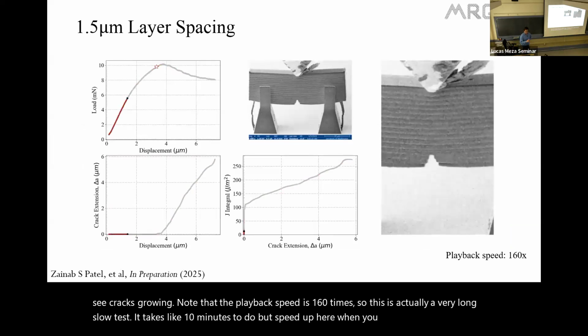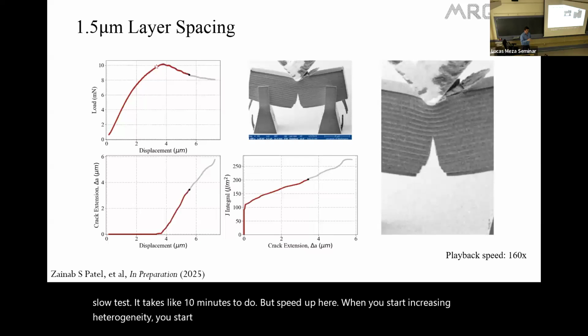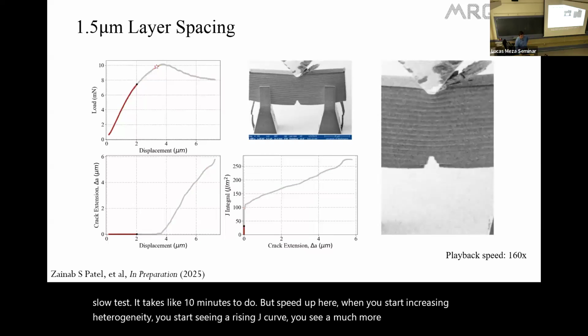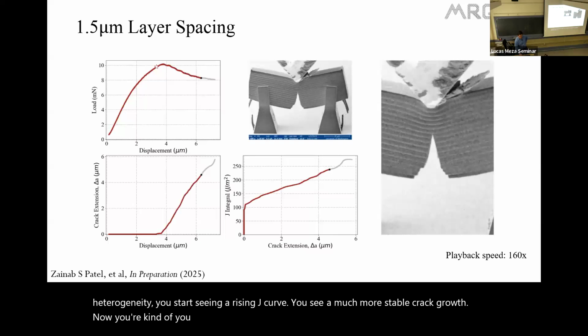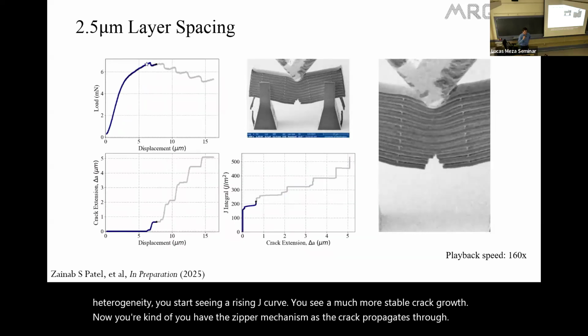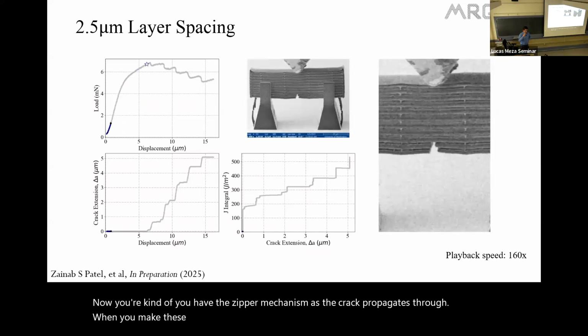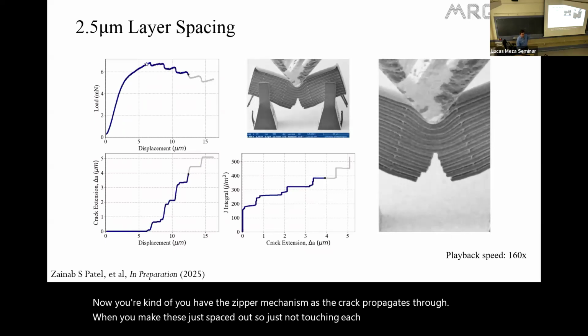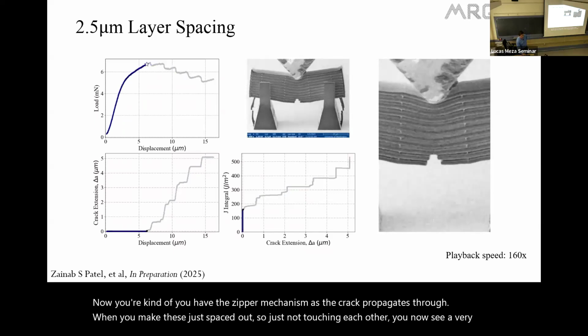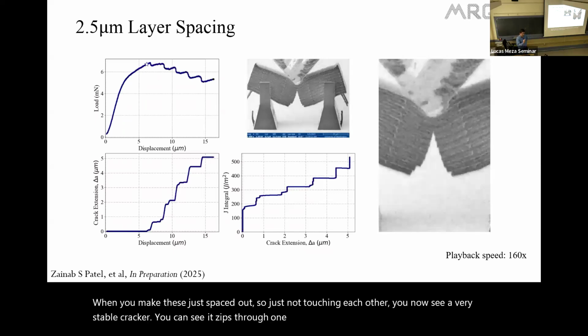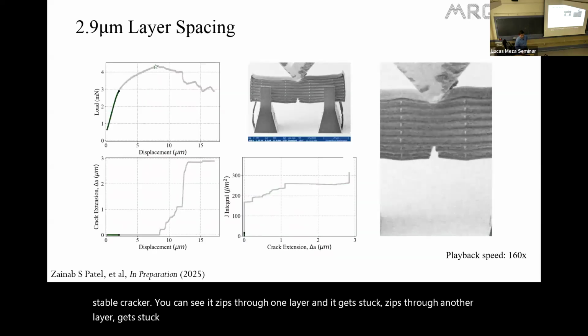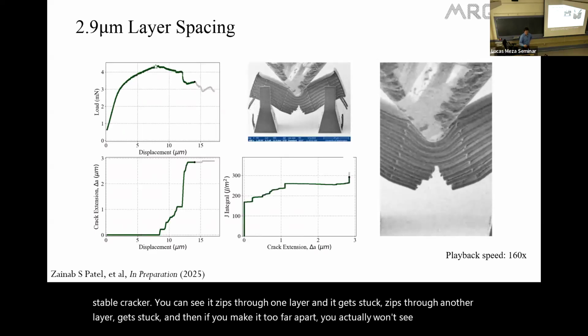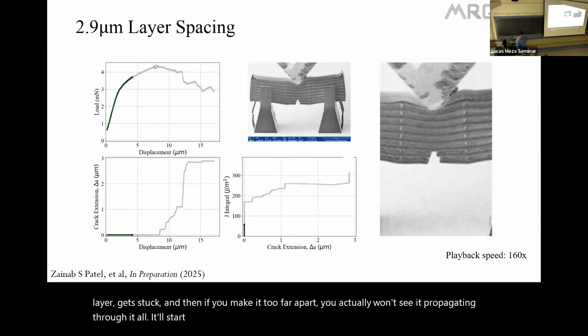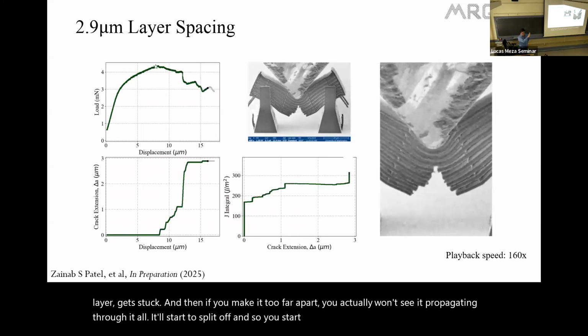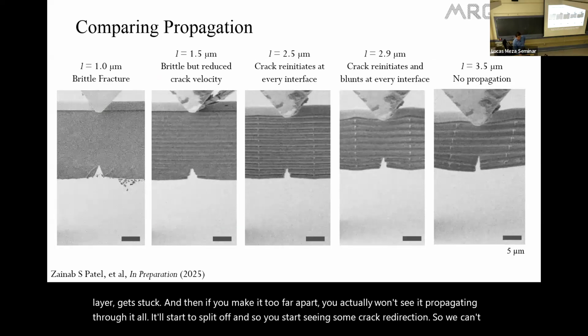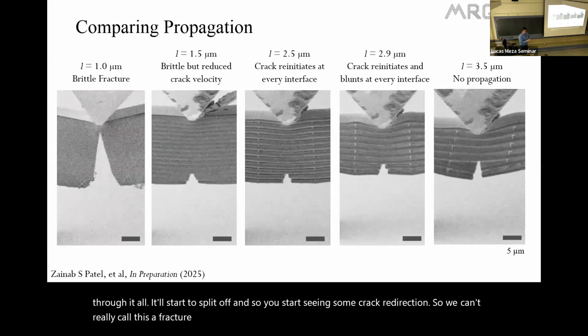When you start increasing heterogeneity, you start seeing a rising J curve. You see a much more stable crack growth. Now you have the zipper mechanism as the crack propagates through. When you make these just spaced out, so just not touching each other, you now see a very stable crack growth. You can see it zips through one layer and then gets stuck, zips through another layer, gets stuck. And then if you make it too far apart, you actually won't see it propagating through at all. It'll start to split off. And so you start seeing some crack redirection. So we can't really call this a fracture property. These are really nice to see all stuck together.